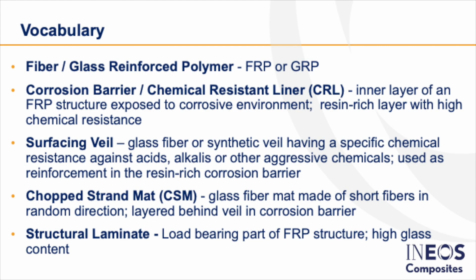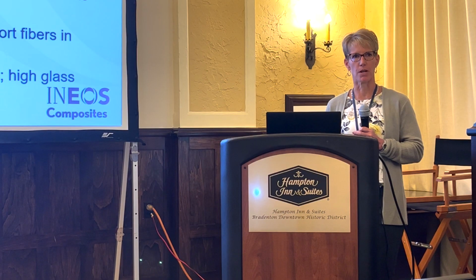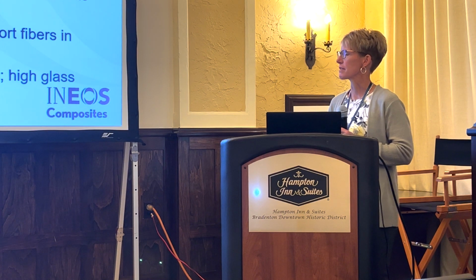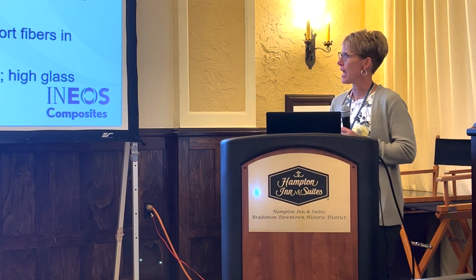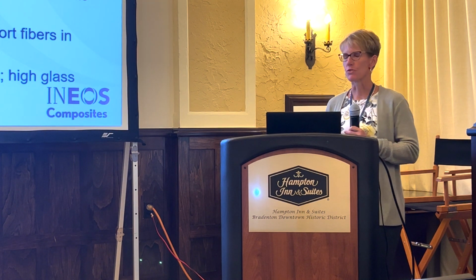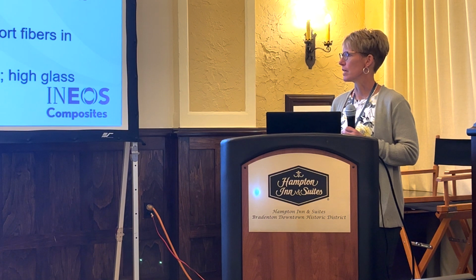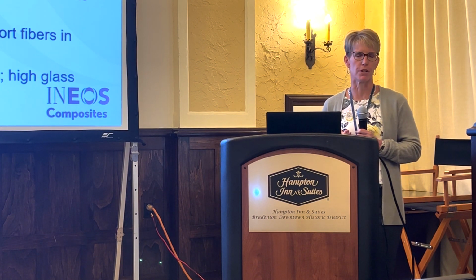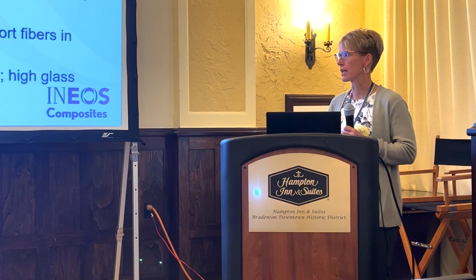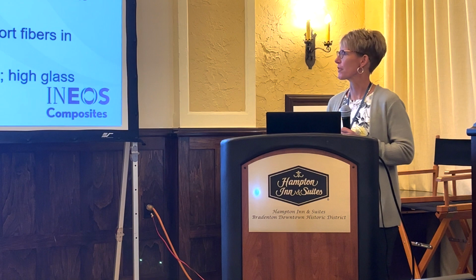Again, a review of some of the vocabulary that Daryl touched on: FRP or GRP, fiber or glass reinforced polymer or glass reinforced plastic, you'll see both of those. The corrosion barrier or the chemical resistant liner, I think by now we know that's the innermost liner that's exposed to the corrosive environment, consisting of a veil layer with a high resin content backed by a couple plies of chopped strand mat. And then chopped strand mat is that fiber that's used not only in the corrosion barrier, but also in the structural laminate, which is going to be that load-bearing part of the equipment with a varying thickness, just depending on the required engineering for that part.